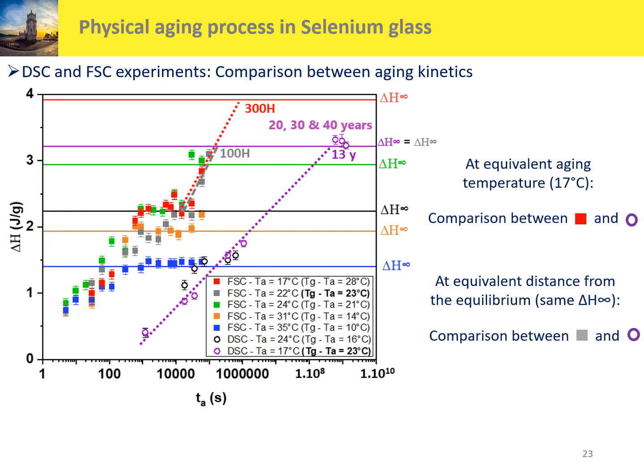So, as you can see here, at equivalent aging temperature of 17 degrees C, by FSC we need approximately 300 hours to reach the equilibrium state instead of 13 years by classical DSC. And if we work at equivalent distance from the equilibrium, we need approximately 100 hours to reach the equilibrium state by FSC instead of 13 years by classical DSC. So it is clear that the physical aging is accelerated by FSC.